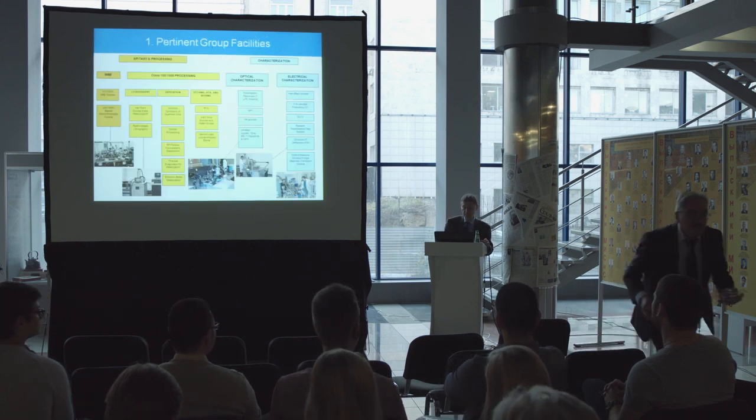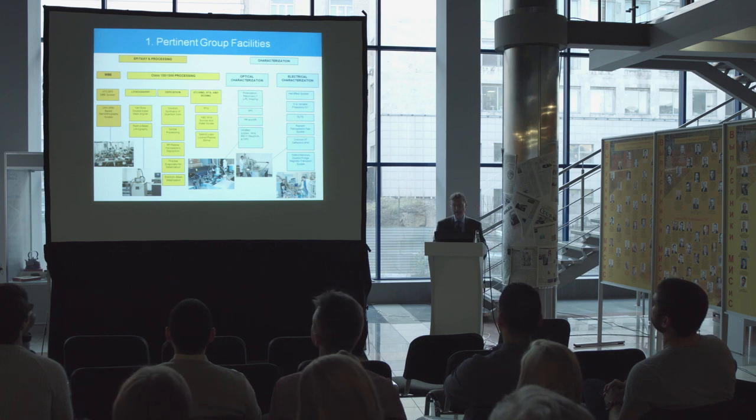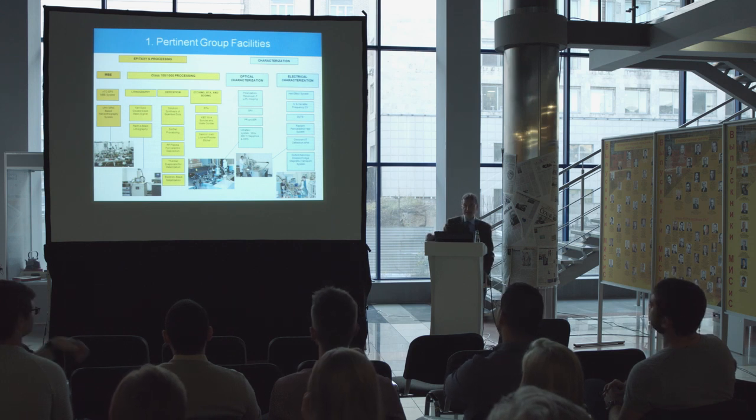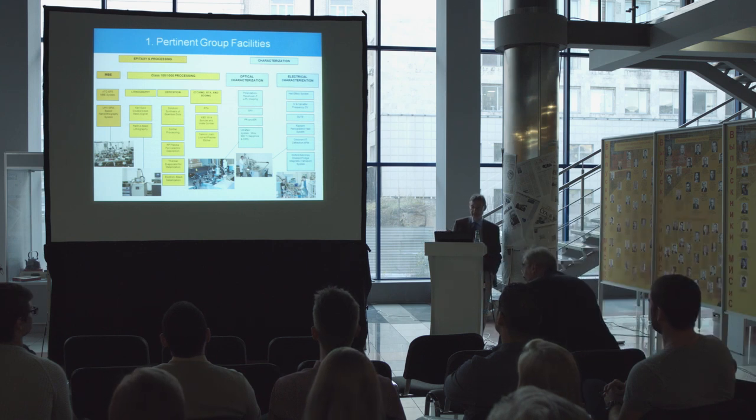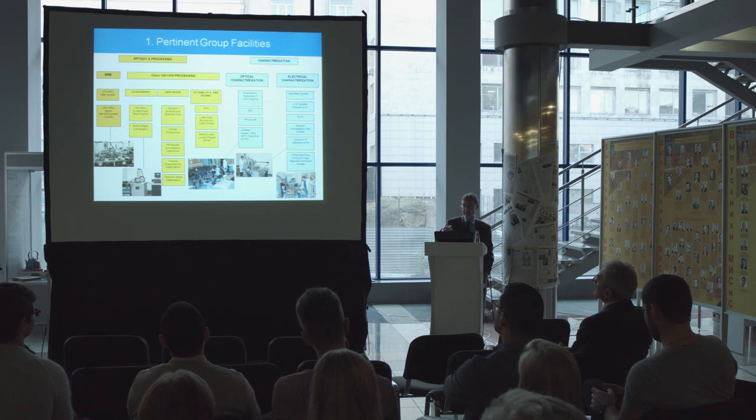I'll begin just by telling you what enables all this research, and that is the fact that in my center and group, we have a lot of advanced growth and processing facilities. In particular, I'll be focusing on semiconductor nanostructures, which means you have monolayer control over the deposition process. MBE, molecular beam epitaxy, is one of the techniques we use a lot, and you can control the growth thickness to submonolayer. With in-situ techniques and characterization, such as RHEED, you can tell where the atoms are sitting and how many are coming in and so forth.